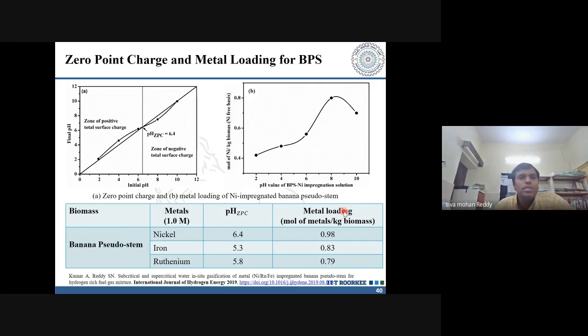Okay, so this is the first part that we are going to talk about, and that is nothing but your metal loading. So how can you load a metal onto a biomass, right? For that, we have taken the biomass and changed the pH of the biomass slurry solution, so that we can load the maximum metal onto the surface. If you look at the zone of positive charge, that is at pH less than ZPC, it is going to have a positive charge. Here your metal ions and the hydronium ions are going to compete with each other, and as a result you see that the metal loading is going to be less over here, right?